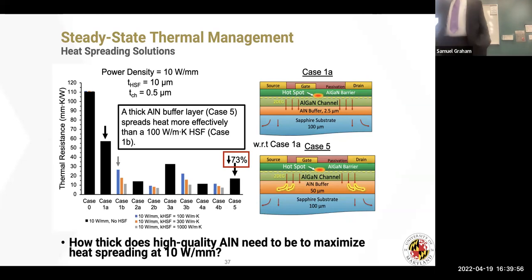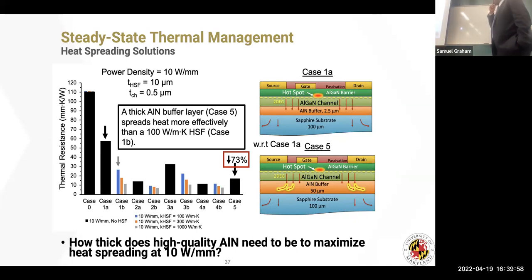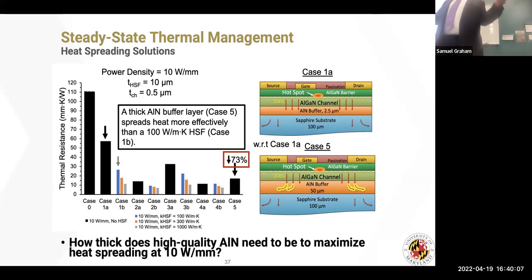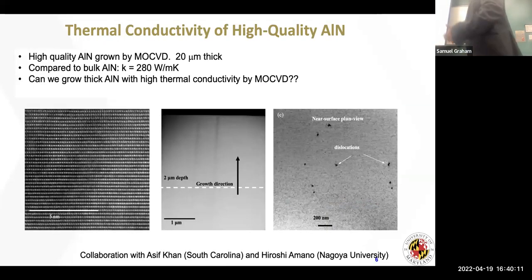One of the issues, as I show this in cartoon form, is that this growth right here is incredibly difficult. The reason why is I start growing the film thicker, a lot of stress, it wants to crack. And so cracking, of course, is no good. And so we have a collaborator, Asif Khan at the University of South Carolina.